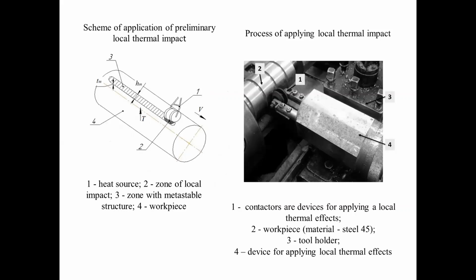The depth of the local thermal impact must be less than the depth of the removed layer of material of the workpiece during subsequent processing. Non-compliance with these conditions will result in two negative consequences. Firstly, the treated surface will have local areas with other physical and mechanical properties than the material of the workpiece, which will have a negative impact on the operational properties of the part.